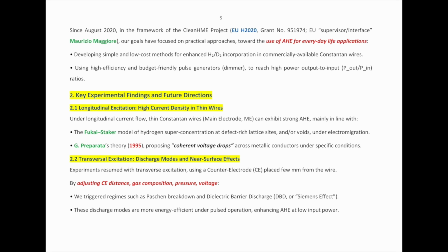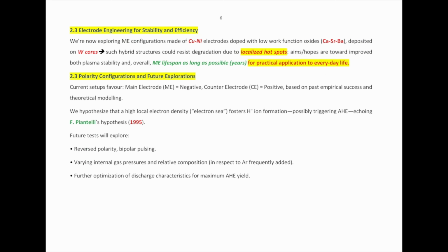Another point is that we have sometimes seen very high temperature melting away the material. We think it's dangerous because it destroys it. So we are now working to have a hybrid system. The bulk is tungsten, which withstands 3,400 Celsius, and over it several layers of copper, nickel, low work function oxides, and so on. We hope it can be a way to reduce the problem of self-destruction of the material, but it is just our hope.